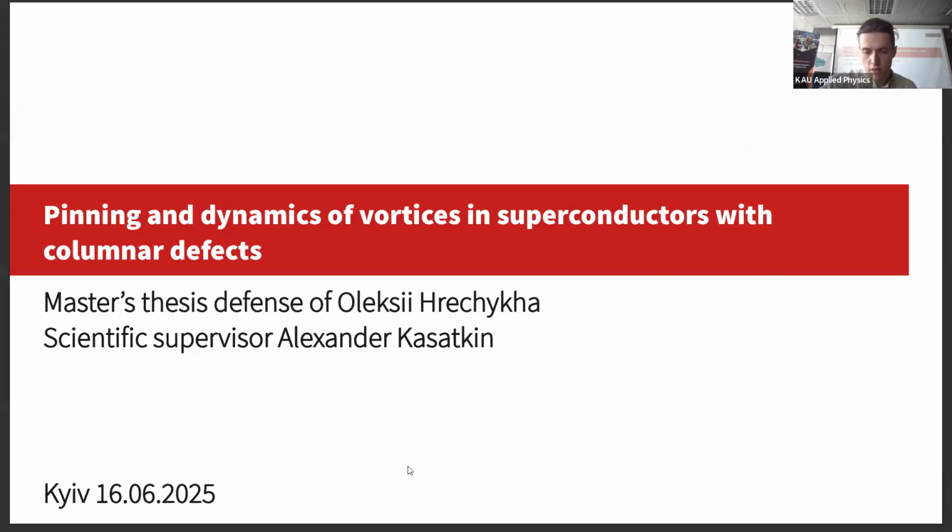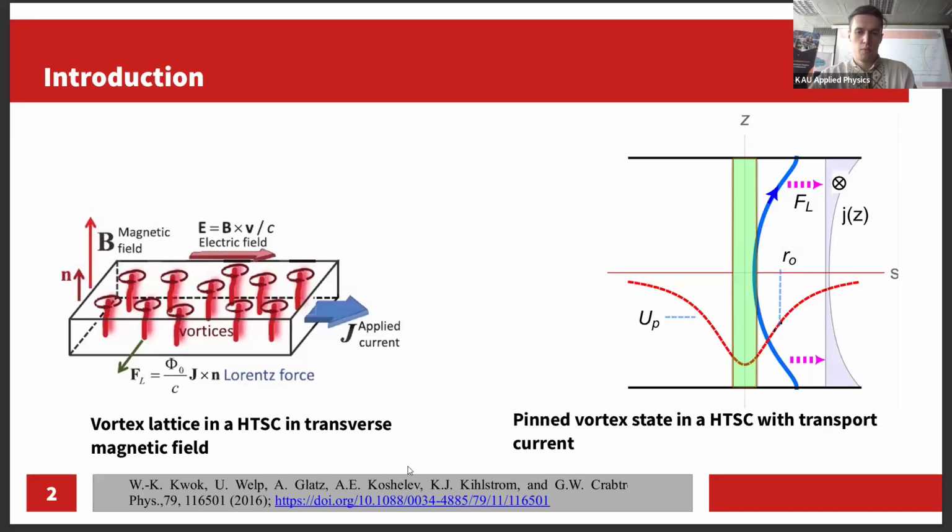The subject of my master's thesis is pinning and dynamics of vortices in superconductors with columnar defects. As you all know very well by this point, the motivation behind introducing pinning is that in a perfect superconductor, an Abrikosov vortex lattice would move when the superconductor is under transport current action or placed in a magnetic field. This movement of the lattice under the Lorentz force will introduce energy dissipation, which is something we want to avoid. And to avoid that, different pinning methods are introduced.